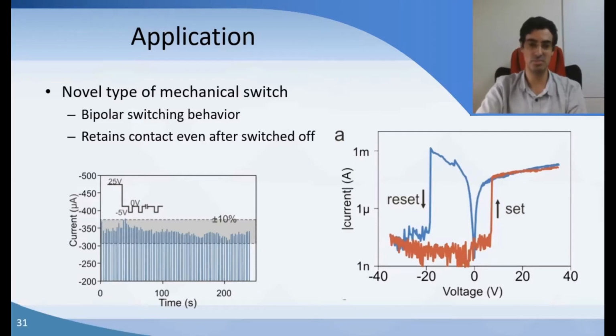And this is only possible because we're combining mechanical and ferroelectrics. So we're making a new kind of mechanical switch, because normally your mechanical switch would have to get in contact and release at the same polarization of voltage. So it's a unipolar behavior. You set at a high voltage, and then as you release, you reset it. So there is no mechanical memory, because if it sticks together at 0 voltage, then it will simply not come off. But in our case, because the ferroelectric can provide reverse polarization to the applied field, we can get repulsive forces. And so we are observing that we can get mechanical switches to reset. So we have a bipolar behavior that is necessary for memory. This is not just a ferroelectric memory, but a mechanical memory.